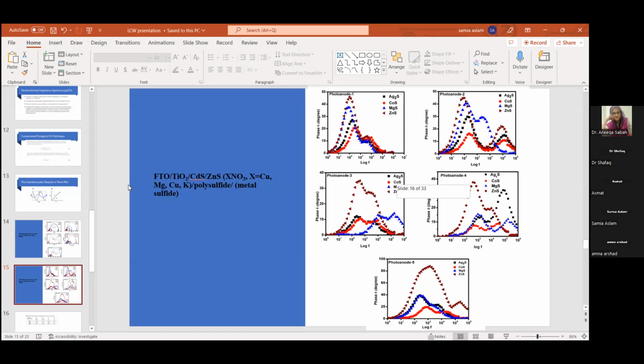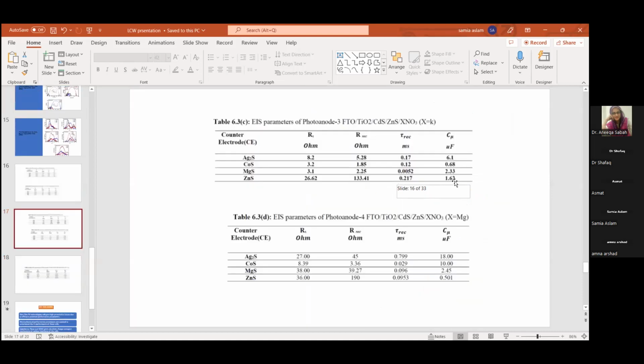So here is the tabular data which I collected, and I have explained the mechanism, how the data was interpreted and analyzed. And similarly, it also helps us to calculate the capacitance using simply the formulae of an RC parallel circuit. And the capacitance means how the interface has the ability to store and release charge. So if the capacitance is high, it means that the interface is very efficient in collecting the charge at one side and releasing it on the other side. So this is how we can relate capacitance to the electrochemical performance of the device.